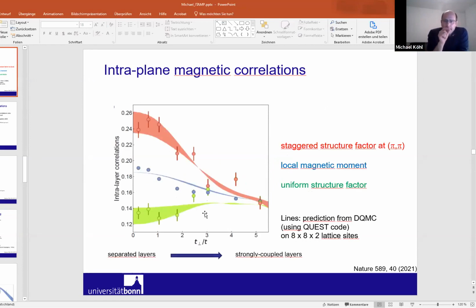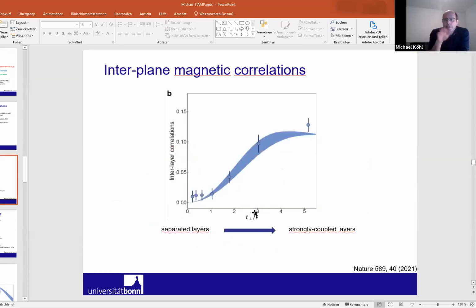You have to be a little bit careful with these numbers, because, for example, in this case we would say there are no magnetic correlations anymore, but we have, because the staggered structure factor coincides with the local moment. Okay, so you say it's more a measurement thing than the correlation actually flattening out? No, I think this correlation does flatten out. In this case, essentially we'll be limited by temperature. Once you increase the coupling between the layers more and more, you will not get more singlet, except for the contribution of the triplet state, which comes in through finite temperature. Okay, but at a lower temperature, you would expect this interlayer correlation to go higher, right? Yes, I think that's a function of temperature. Okay.